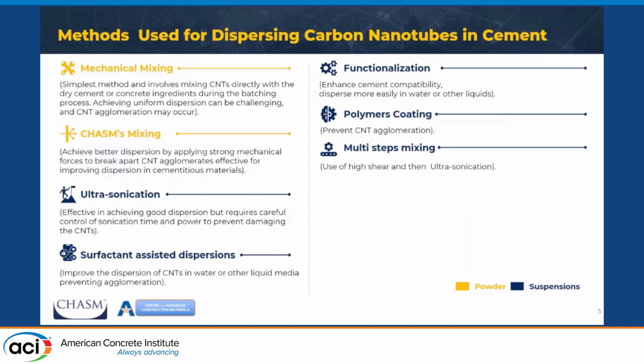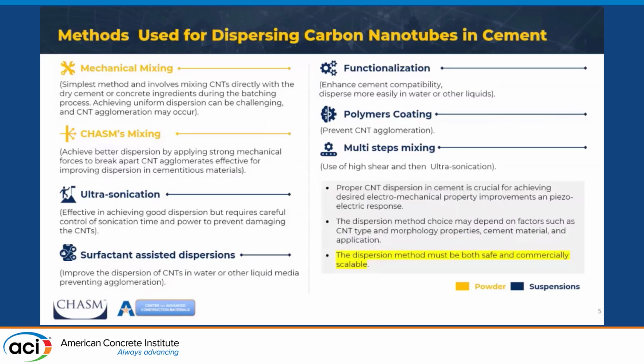Because dispersion is one of the issues, there are at least two methods for dispersing nanotube in cement. One method is blending mechanically powders of cement with the carbon nanomaterials, and the other is preparing a suspension of carbon nanotube. But why do we need high dispersion? Because the dispersion has an important impact on the performance of the cement. And choosing the appropriate dispersion method depends on several factors, for instance, the type of carbon nanotube and its morphology, the properties of the cement material, and also the specific application. But I would like to highlight that the method for dispersing carbon nanotube must be both safe and commercially scalable. If this is not clear, we cannot get a commercial product.